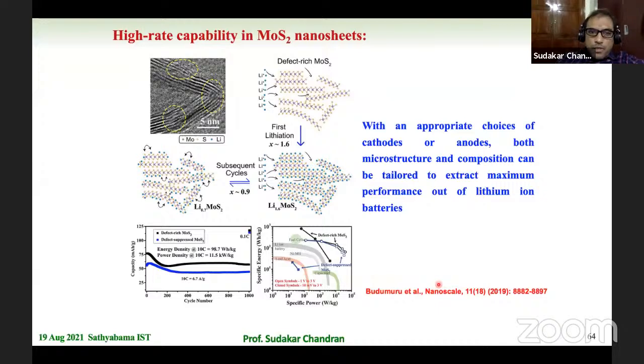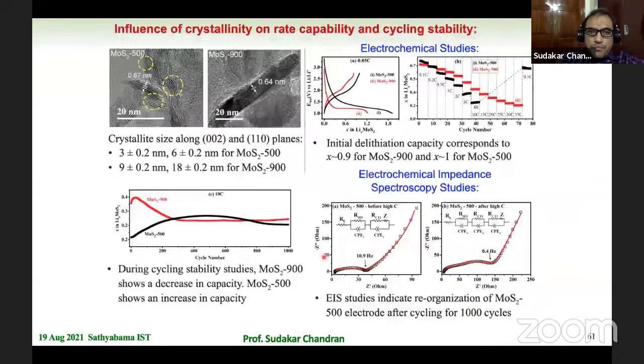Just to summarize, these defect-rich molybdenum disulfide materials give a very high specific energy density and specific power density. But the challenge is, as I showed, cycling between 1 volt and 3 volt gives only a maximum capacity of 150 milliampere hour per gram, while carbon is 350 milliampere hour per gram. We did study these electrochemical properties by going below 1 volt, all the way close to zero, and that I did not present.